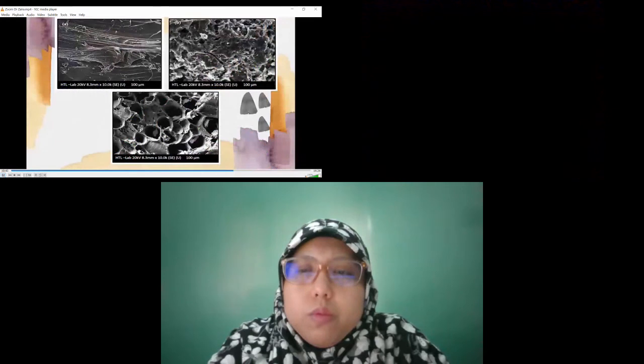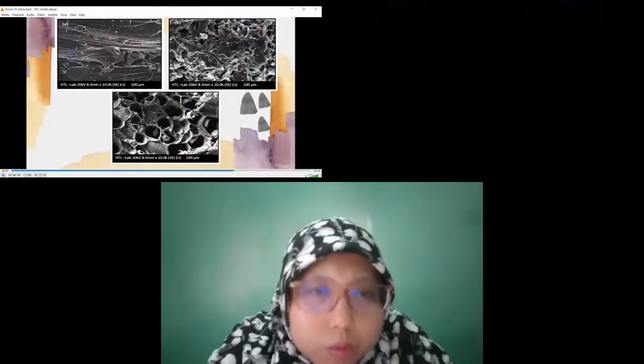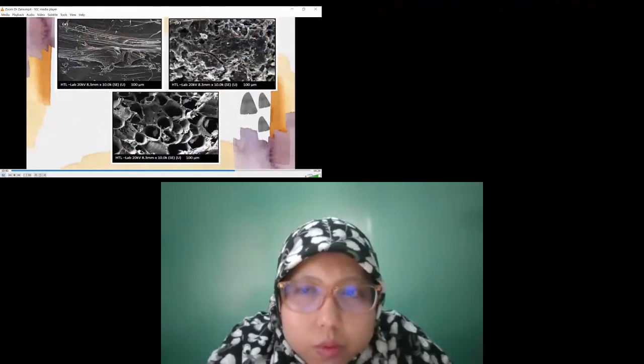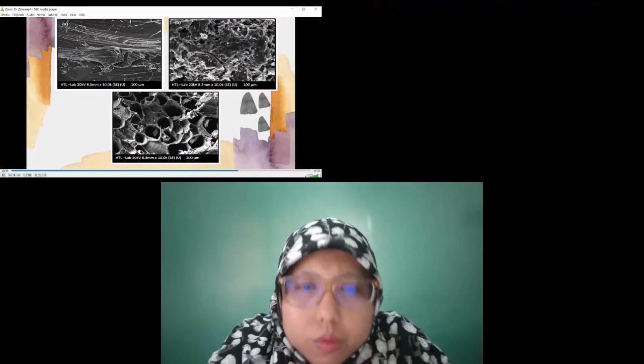This is our surface FESEM. We can see that the first picture is our raw biomass. We can see a cuticle layer which is quite smooth and there is no pore. After carbonization, a small amount of pore has been developed, and after activation there are a lot of pores. Inside the mesopore wall there are micropores also.